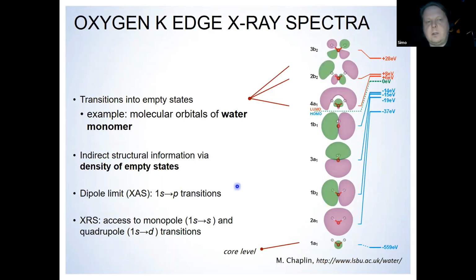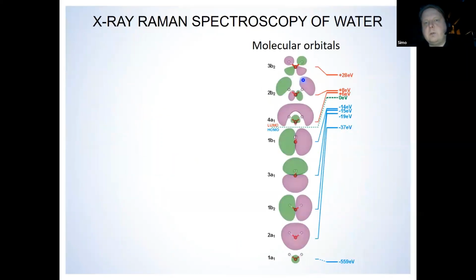And at the dipole limit, the X-ray absorption spectrum is limited to dipolar s to p transitions, but X-ray Raman spectroscopy gives also access to other excitation channels. So it's in principle a tool also to look at other molecular orbitals that would be otherwise forbidden in regular X-ray absorption spectroscopy. So what one expects to see is that we come in with a photon that excites the inner core shell electron and puts it into the unoccupied orbitals. The first one here, in the gas phase, is a strong pre-peak that will actually be seen also in condensed phase water systems. Then we measure the intensity of the outgoing photons and their energy spectrum.